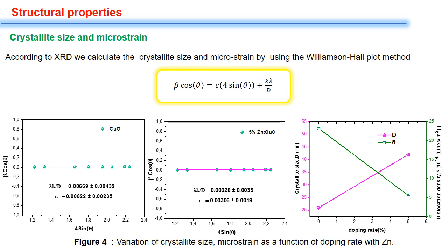According to XRD, we can calculate the crystallite size and microstrain using the Williamson-Hall plot method. This figure presents the variation of microstrain and crystallite size as a function of zinc doping rate. The crystallite size of our films varied between 21 nanometers and 53 nanometers, and increased with increasing doping.